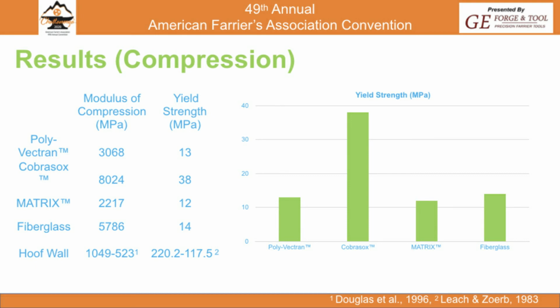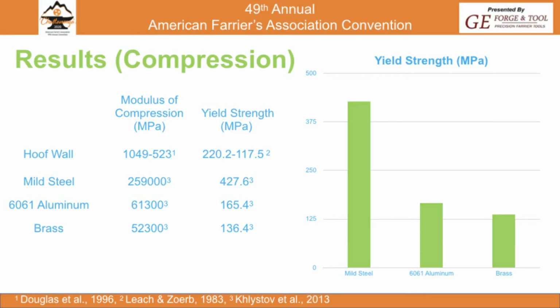And so luckily, when we look at them, so again, there's no blue line because they're all lower than hoof wall, so it would be way up there about the light. Okay. So from the bottom, so naturally, it's very, very nice to think, oh, well, we should include the metals and do the exact same things to them, but luckily these very nice students at MIT had already done that with actually the most common things we use to repair hoof wall with. So they did it with 6061 aluminum, brass, mild steel, and so we were able to take their numbers and compare it with hoof wall. And again, hoof wall, like I said, there's a big difference between outer non-pigmented stratum medium and inner pigmented stratum medium, and then even outer non-pigmented stratum medium. They're all quite different, so that's why they're reported in a range.